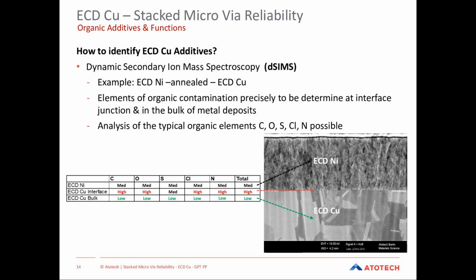contaminated with these elements. So you see here at the interface between electrolytic copper and electrolytic nickel, especially for chloride and nitrogen, higher readings, which means at the end, very likely these are co-deposits from the electrolytic copper process, and the electrolytic copper bulk analysis shows that these elements are quite low in concentration. So you already see here nucleation interfaces are prone to higher adsorption of plating additives, and by these two methods, by STEM and DSIMS, you have a chance to analyze these element concentrations and have an idea, okay, which process maybe lead to a weakness of this interface integrity between stacked microwires.